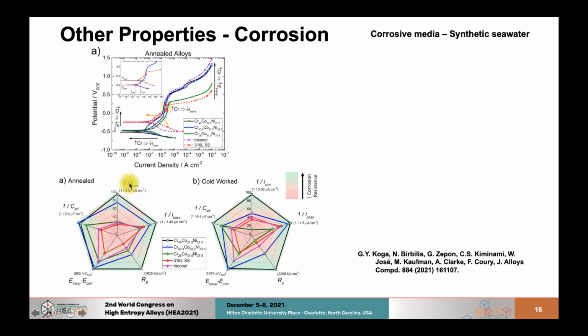Another thing that should be mentioned here is corrosion resistance, and these alloys do display outstanding corrosion resistance in synthetic seawater. By doing potentiodynamic polarization and impedance tests, we show that especially when you go to alloys that are richer in chrome, we do observe a great increase in the corrosion resistance. So all these parameters here we selected to compare different alloys. We show that, for example, the alloy with 45% chrome is better than the equiatomic alloy and better than an alloy with lower chrome content.